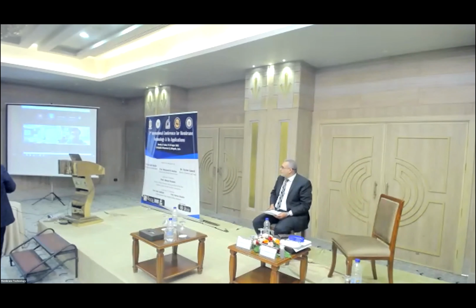There was this gap, and the simulations sort of tell us how domain size will scale with molecular weight. More of what motivated the molecular weight and composition we targeted was that we found in prior work that you really need about a 50-50 fraction to get that balance of mechanical strength and high selective transport of species.